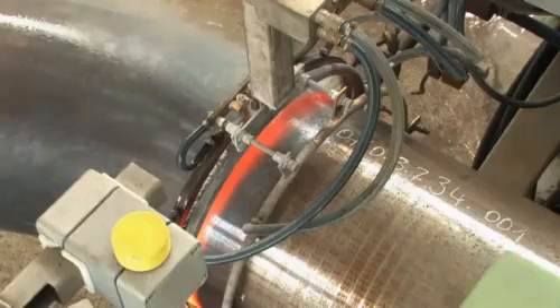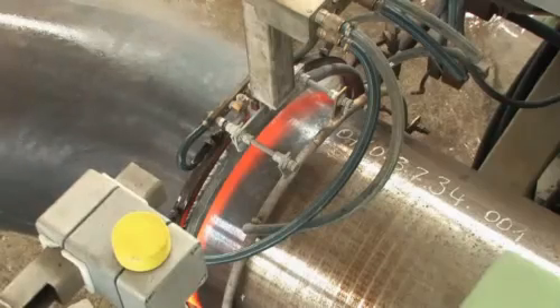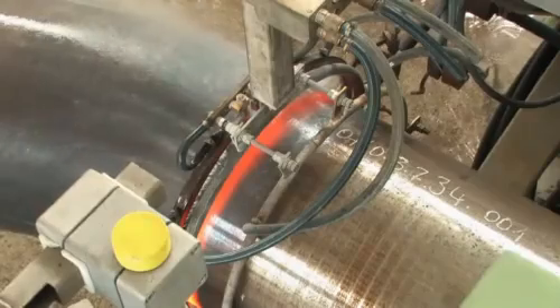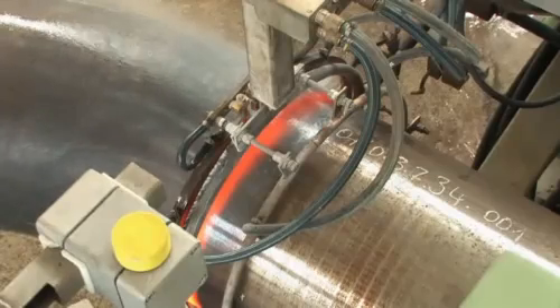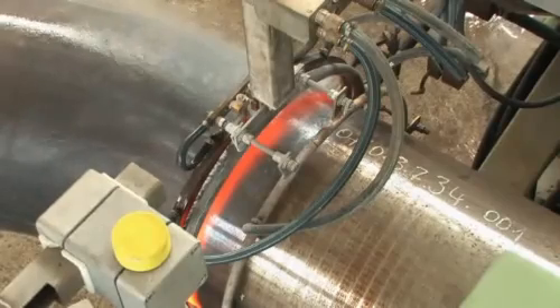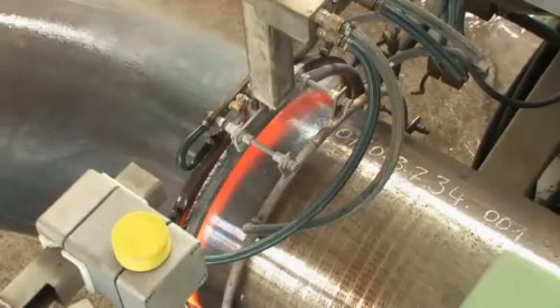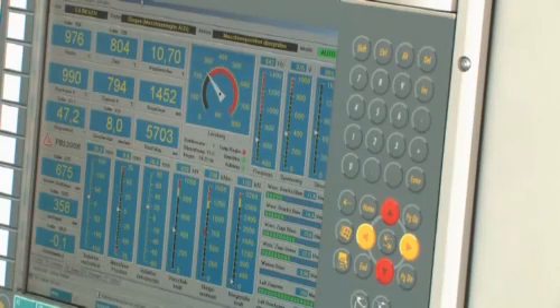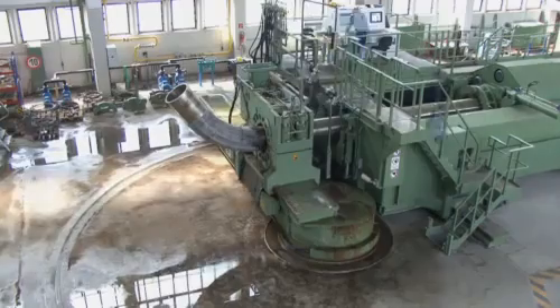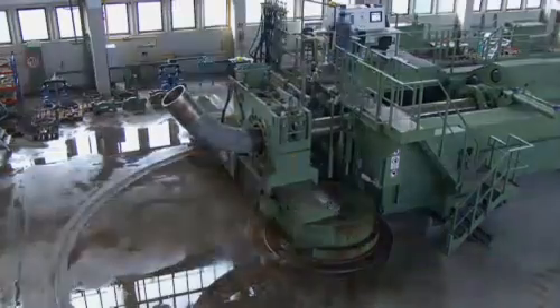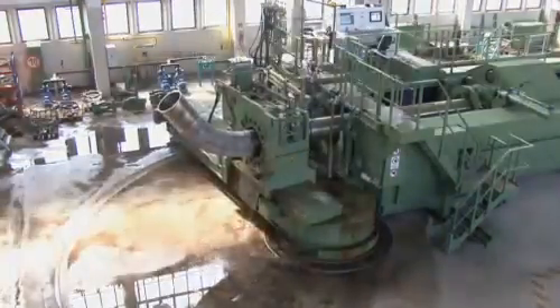The ratio between the bending radius and the pipe diameter greatly affects the ovality of the bend. In this case, it is 2.8. The feeding is carried out at a rate of 8.0 through 9.5 millimeters per minute. The bending process has started. The heating unit is charged with about 250 kilowatt. The bending moment amounts to about 700 kilonewtons. At the selected feed rate, the actual bending process lasts 5 hours.